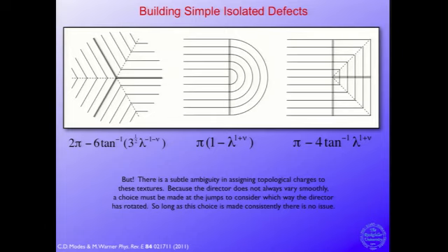And in two dimensions, it's a happy coincidence that the angular deficit or the angular surplus is identically equal to the Gaussian curvature charge at a point. So this gives you a direct, and a very easy, way of calculating the development of Gaussian curvature at each of these points. It is an isolated point of Gaussian curvature, and so it must be conical again, conical or anticonical.